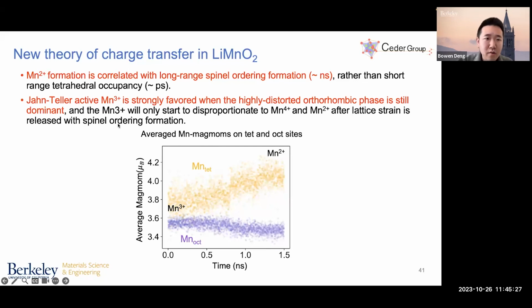And this result actually tells us that this manganese 2+ formation is correlated with a long-range spinel ordering formation, which we see in the MD is around the timescale of nanosecond, rather than the previously proposed short-range tetrahedral occupations, which is around the timescale of picosecond. And we rationalize this observation by arguing that these Jahn-Teller active manganese 3+ ions, which are dominating the species in the initial cell, are actually highly favored when the highly distorted orthorhombic phase is still dominant. And the manganese 3+ will only start to charge disproportionate to manganese 4+ and manganese 2+ after the lattice strain is released with the spinel ordering formation, which is at the time scale of nanosecond.